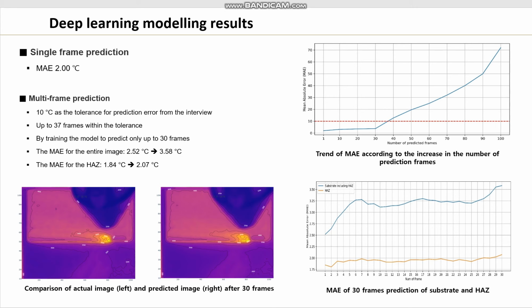The entire coating layer and the shape of the heat affected zone were accurately predicted without blurring the boundary of the image. On the other hand, it is necessary to get information about multiple future states for effective control in model predictive control. So, we conducted an experiment on multiple frame prediction of the thermal profile. First, we calculated the maximum number of time steps that can achieve stable prediction accuracy, even if a prediction point is far away.